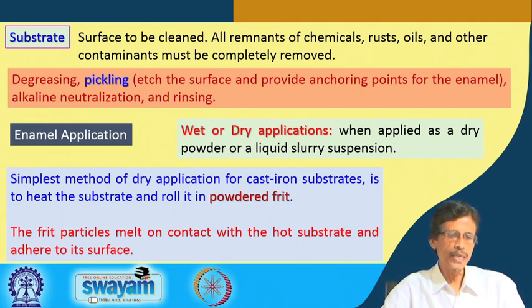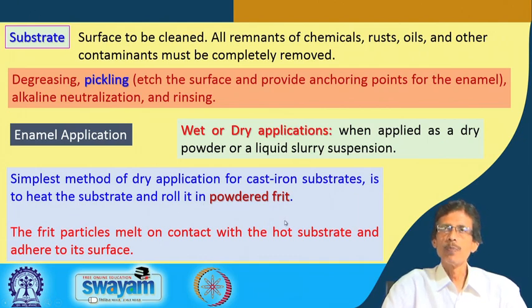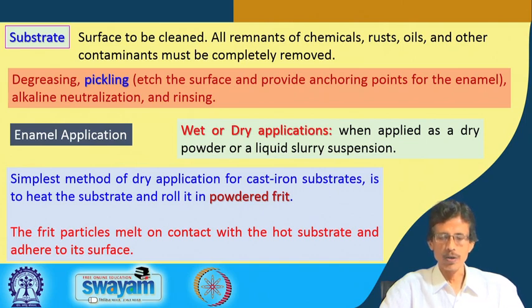So, this thing can be heated. Heat the substrate and roll it in the powder frit. So, the powder frit is there, and the heated substrate or container is basically rolling on that dry powder. At that particular temperature you can have the fusion of the frit material, and the frit material is attached to the substrate. So, this is one particular technique. The frit particles fuse together, that means they melt on contact with the hot substrate, because that material is hot enough to melt your frit powder and adhere to its surface. It is a very simple technique: you have the heated substrate, that means the heated container, and it is fixed with your enamelling powder.